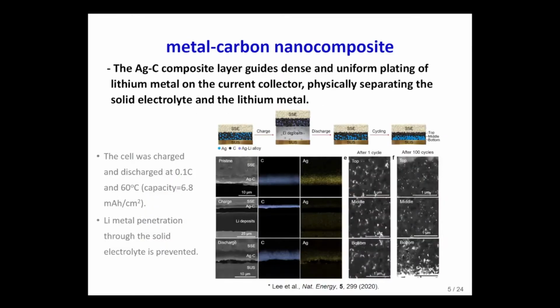This slide shows how this system works very well. In the first charging process, a dense lithium metal layer is deposited between the silver carbon layer and the stainless steel current collector. No lithium metal is found above the silver carbon layer. Some silver is dissolved into the lithium metal during this process. If we discharge the cell again, the lithium metal layer is completely removed. Some silver is accumulated at the bottom of the silver carbon layer.